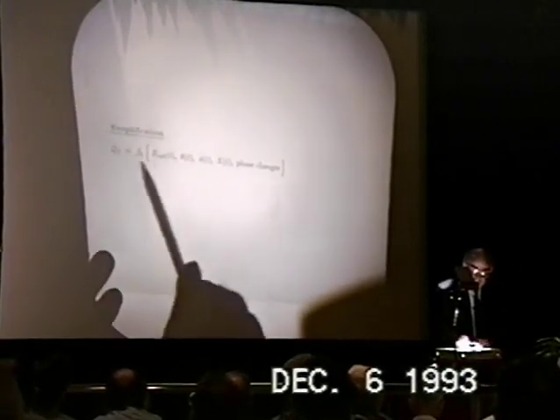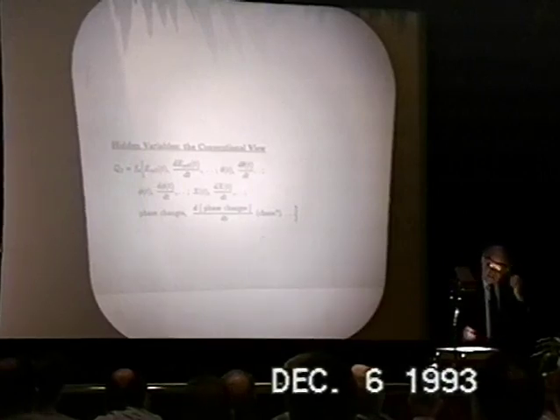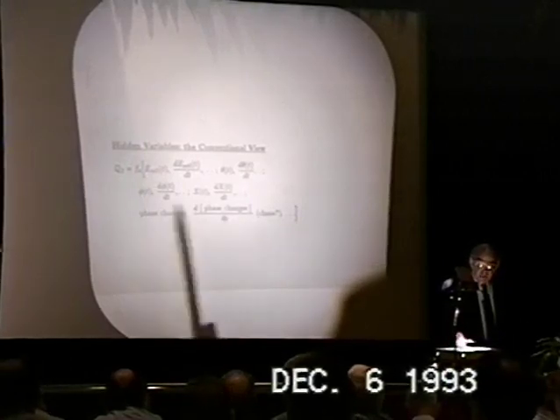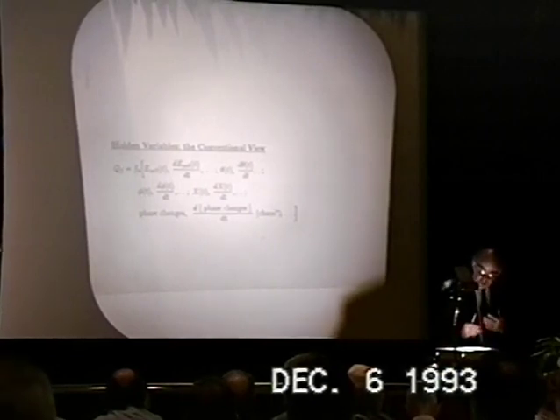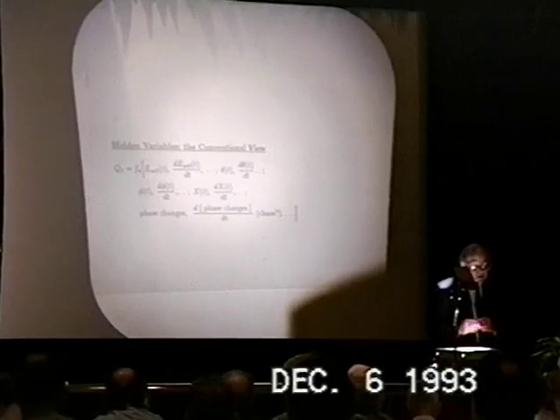endothermic regime. And you see immediately that the outcome of your experiment will depend on the experimental protocol you adopt. All right, so we see that we have to deal with a time-dependent system, and we see chaos, and we have to ensure that we can push the system sufficiently rapidly through the exo-endothermic transition to ensure that we can achieve high loading and high temperature. I'll come back to that point in due course.